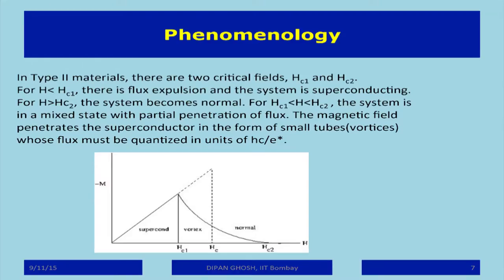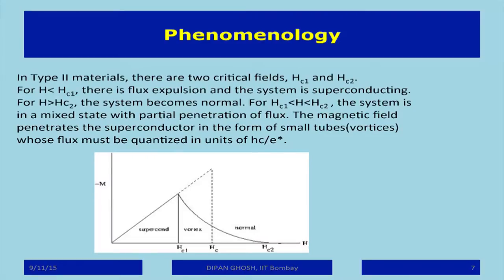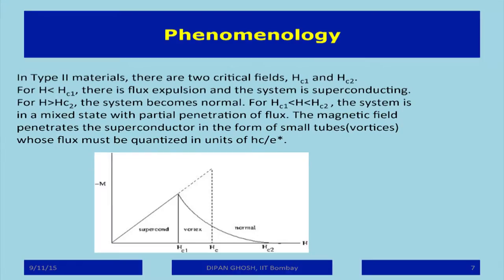Now, what we do is keep these materials at a particular temperature and increase the magnetic field. Below a particular value, the material remains a superconductor. But when the field exceeds a value which I call Hc1, there is some expulsion of flux, but it is an incomplete expulsion of flux. Remember that the Meissner effect says that a superconductor doesn't allow anything to get in. If the strength is large enough, which we'll call Hc2, the material will become a normal metal.